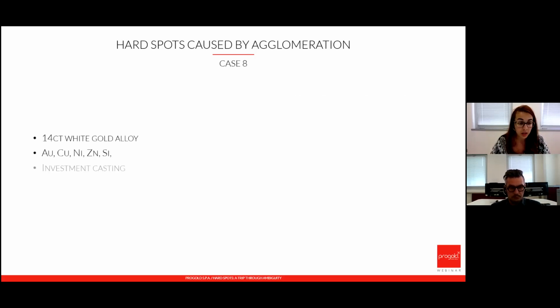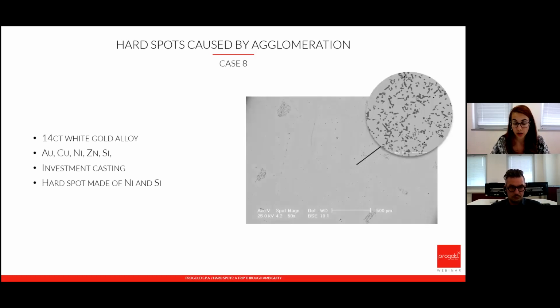In this case, we have a similar case to the one I told you about when we were talking about the crucibles, which is nickel and silicon. Also in this case, the reaction was not due to the fact that we were using the wrong crucible or the wrong materials for casting. It was due to the fact that we were enriching this alloy in nickel and silicon, and at some point they decided to react among themselves.